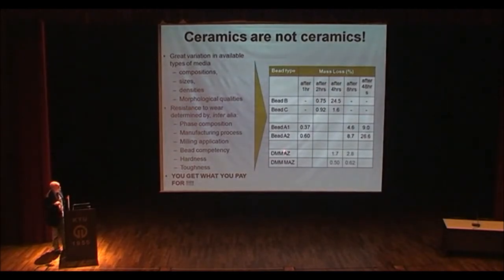And again, composition can have an effect. This is our own product, 2 different compositions, and you can see that there's a significant difference. This is a much harder version, a tougher version. But the only difference there is not the composition, it's not the size, it's not the density, it's actually the way the processing is done.